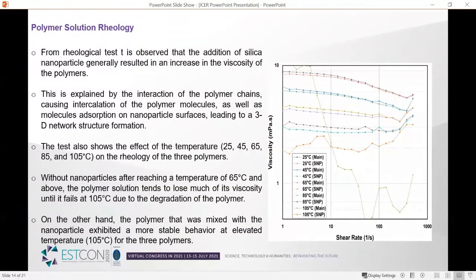We also looked at the rheology of the polymer at temperature from 25 to 105 Celsius. And we observed that the addition of the silica nanoparticle generally results in the increase of the viscosity of the polymer. Without nanoparticle, however, after reaching a temperature of 65 Celsius and above, the polymer solution tends to lose much of viscosity until it fails at 105 Celsius. And that's because of the degradation of the polymer at that temperature.